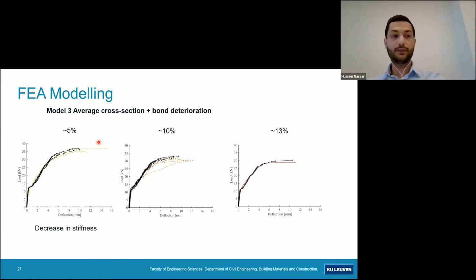For the third model, I took into account the bond deterioration based on the calibrated curve, as I explained recently. A decrease in stiffness has been observed, which agrees well with the one in the experiments. Yet splitting cracks were still not observed, especially in the case of the beam which shows the least stiff behavior and the most deterioration in terms of bond stiffness. It could be possible that in the calibrated bond slip curve, the slip which is taken into account is too low, whereas for a beam to show excessive slip, the calibrated deterioration curve should predict a bond failure at a higher slip value.